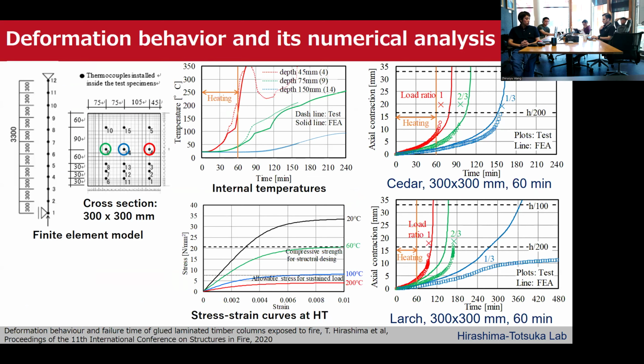Numerical analysis was also carried out on the deformation behavior of the column subject to fire heating. This figure shows a finite element analysis model. The internal temperature result from the heat transfer analysis approximately agrees with the experimental temperature measured at this point shown in this figure. Thermal stress analysis was conducted using stress-strain curves at high temperatures with reference to the Eurocode reduction factors.